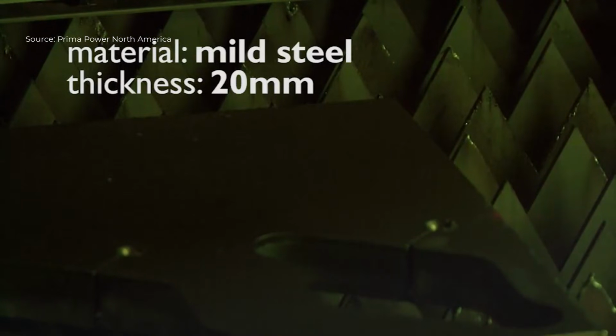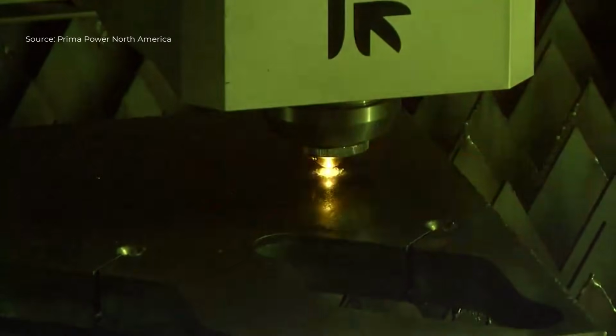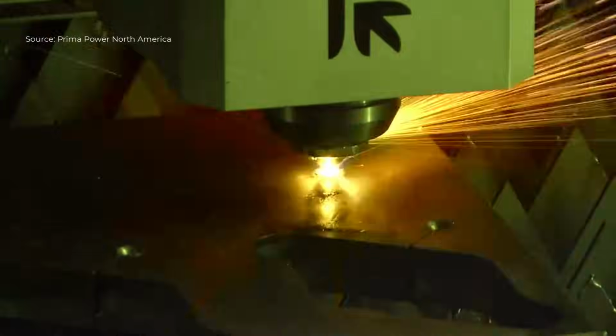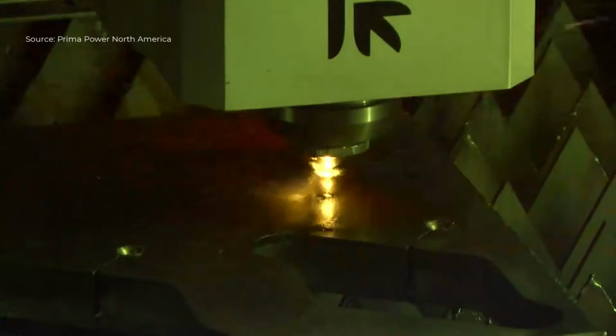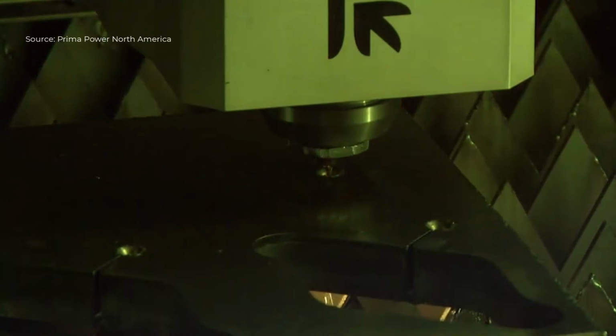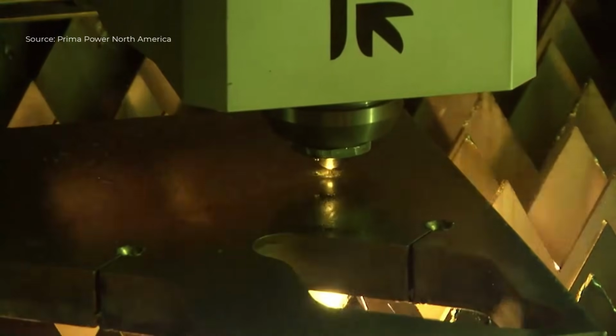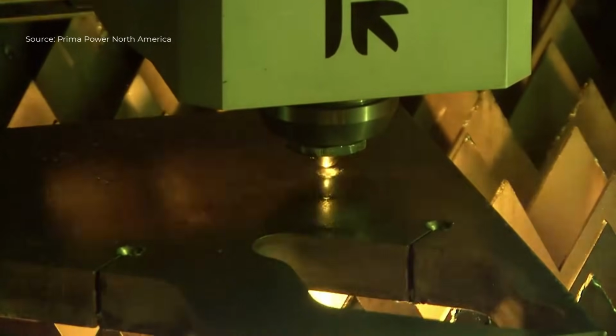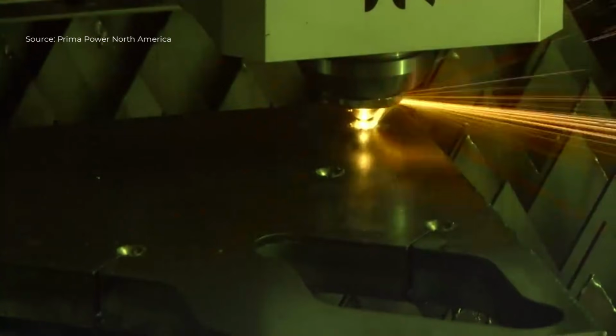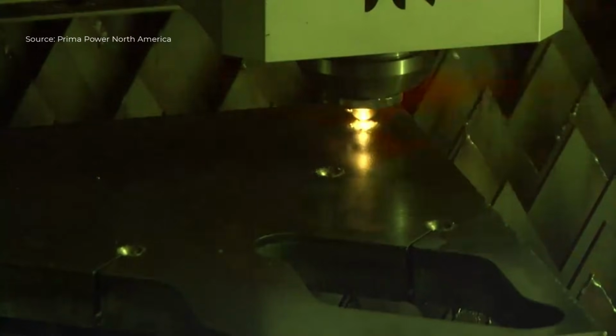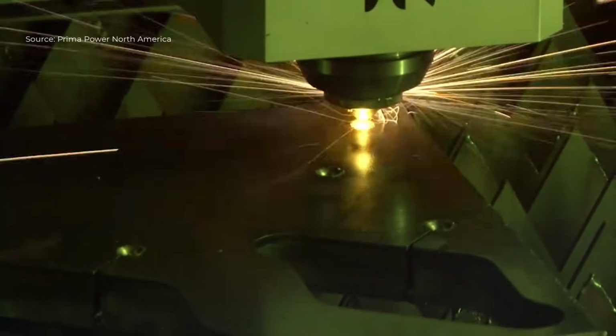As the cutting process progresses, the machine demonstrates its capability on even thicker mild steel, reaching a thickness of 20 millimeters. The cutting parameters are again automatically adapted by the control system. The piercing phase is executed with precision, gradually penetrating the material layer by layer. This controlled approach ensures reliable piercing while protecting the cutting nozzle and optics. During cutting, the laser beam remains stable, and the cutting head maintains accurate positioning even over longer cutting paths. The result is a clean separation of the thick steel plate with minimal slag and consistent edge quality.